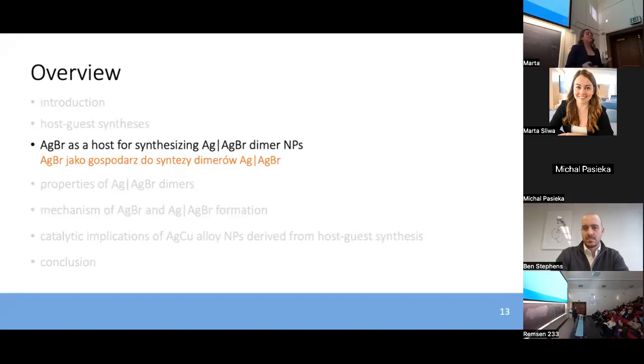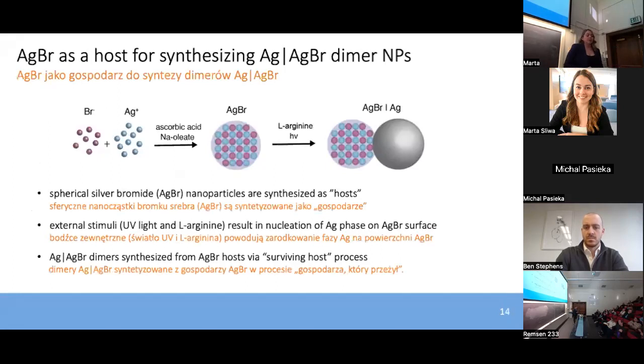So we used the basis of host-guest interactions and put the advantages of this technique into practice and developed a new synthesis to make multi-component silver-silver bromide dimer nanoparticles. Our host-guest approach involves using silver bromide nanoparticle intermediates as platforms for the formation of that final heterostructure, that silver-silver bromide dimer. The formation of the silver phase of this dimer occurs when we expose the silver bromide host to external stimuli, which is what we call the dimerization process, so that will come up again in my talk. That process is when we expose the silver bromide to UV light in the presence of a molecular reductant, L-arginine. In this way, we use the silver bromide host to create these dimers by way of that third category of host-guest syntheses, surviving host processes.